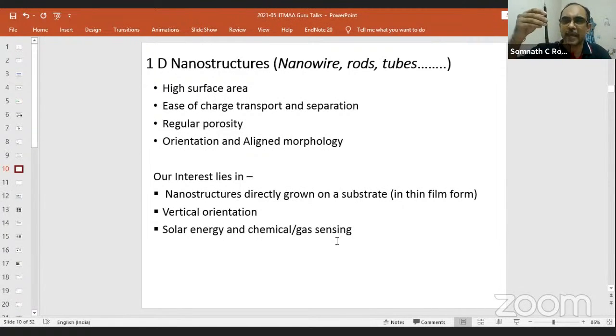Consider this pen as my nanostructure, and you shine light on it. What will happen? As I said, electron hole pairs will be generated, right? Now, this kind of one-dimensional nanostructure already has the property of nano, which is high surface area. If the electrons are generated inside, they can flow only in one direction. There is not much scattering here and there. Regular porosity, I will show what I mean by that. Orientation and aligned morphology: we want all our nanostructures in a particular orientation. We do not want too much randomness in the whole.